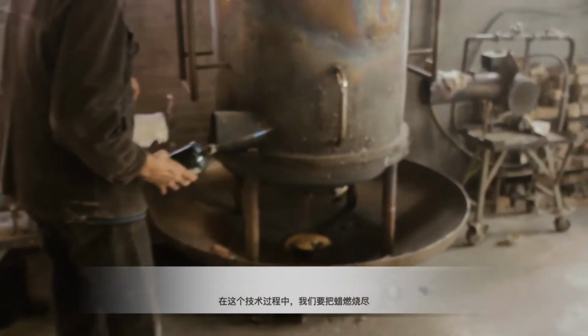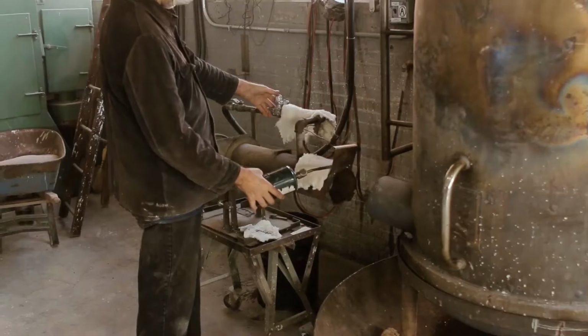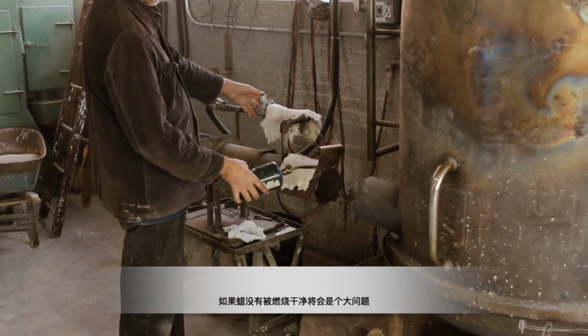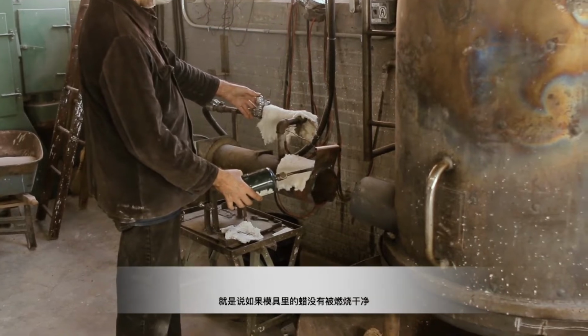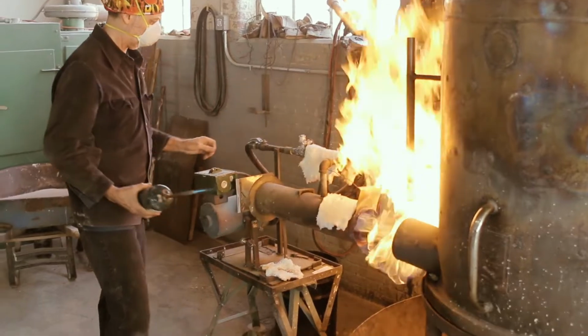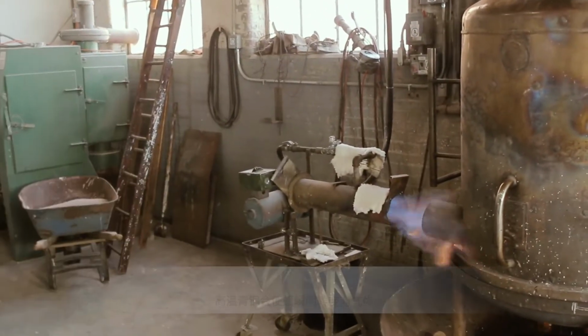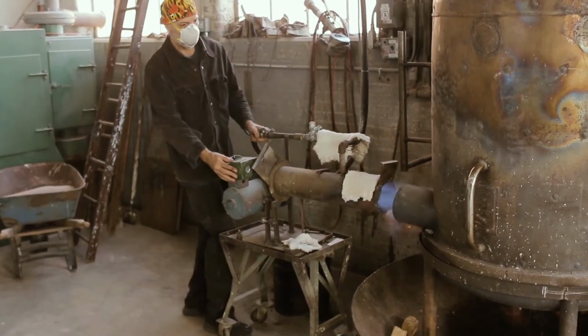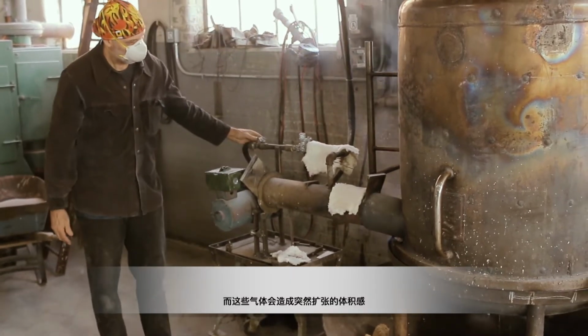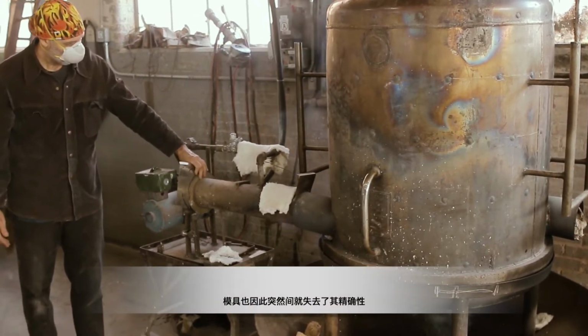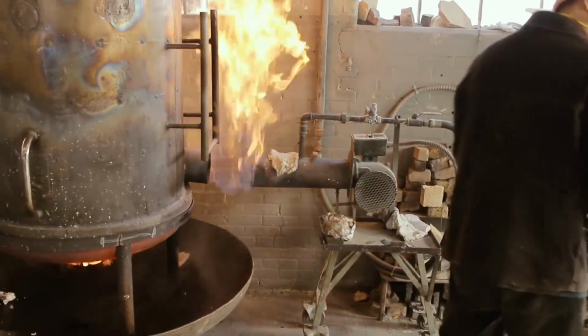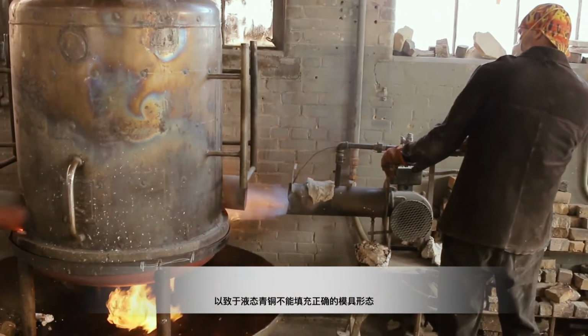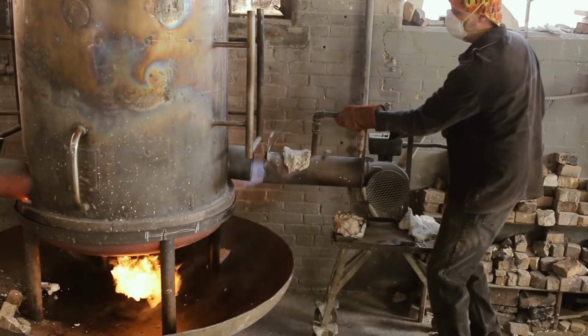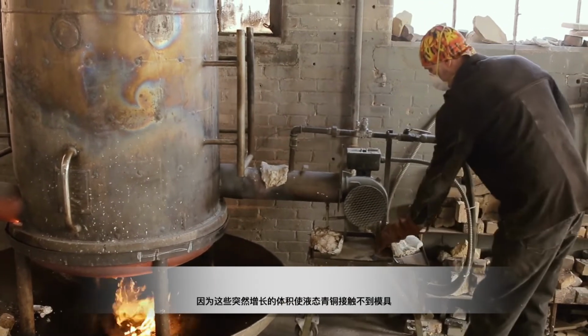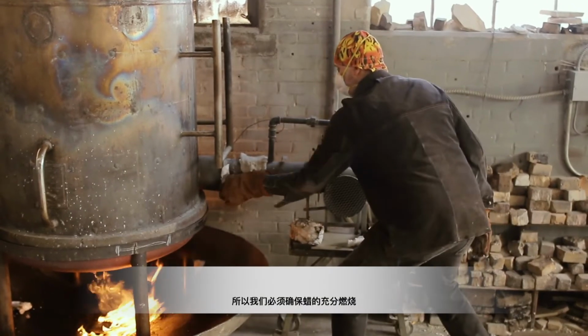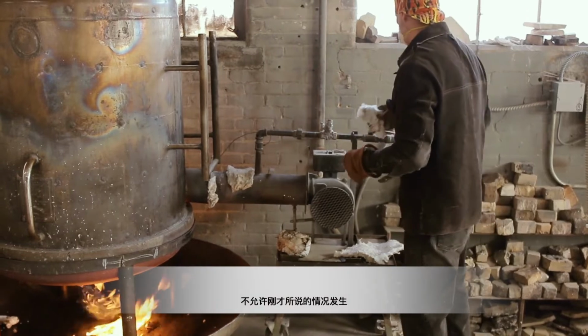It all comes out. We burn it and burn it and burn it until there's nothing left in there. If the bronze came in contact with wax, it would be a real problem. And by that I mean if wax wasn't completely burned out of a mold and we poured bronze into it, the bronze would make the wax immediately turn to a gas. And a gas is a sudden expansion of volume, and the definition of an explosion is a sudden expansion of volume. So the bronze still being liquid could quite well shoot back up out of the mold because of the explosion of wax in contact with bronze. So we make really sure to burn these molds out clean and not let that happen.